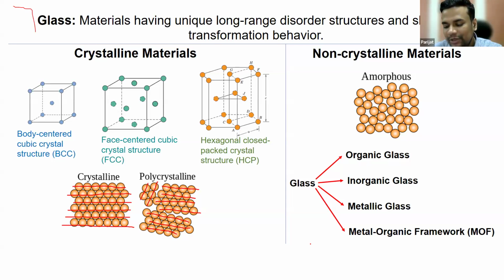So when Paul Duwez was doing the experiment, ideally the 75% gold and 25% silicon should form a crystal metal like this, where the gold and silicon atoms will arrange in a particular way like this. But by doing this splat quenching, the alloy was so rapidly cooled that the crystal structure got destroyed, and the atoms became frozen in the liquid state. In the liquid state, the atoms are randomly arranged.